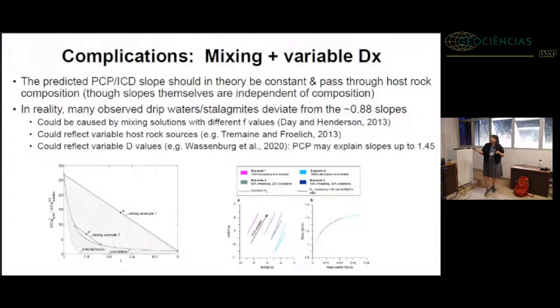On the right here is another figure from Wassenberg et al. in 2020, where they basically, based on that relationship they found between the magnesium-calcium content of the calcite and the distribution coefficient for strontium, found that changes in the distribution coefficient could mean that slopes that previously were rejected as too steep for PCP may actually be explained by PCP if you have a varying distribution coefficient within the range that they found.